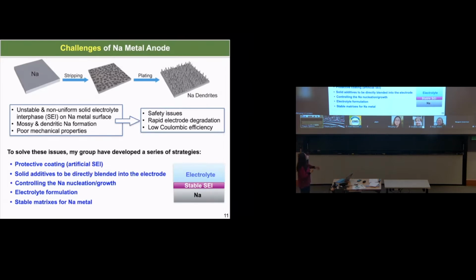a uniform sodium deposition. Of course, we also work on the electrolyte formulation, and we also try to find a stable matrix. The schematic I show here is a porous carbon matrix. We can directly infuse sodium into the matrix to further improve both the mechanical property and the chemical and electrochemical stability of the sodium metal.